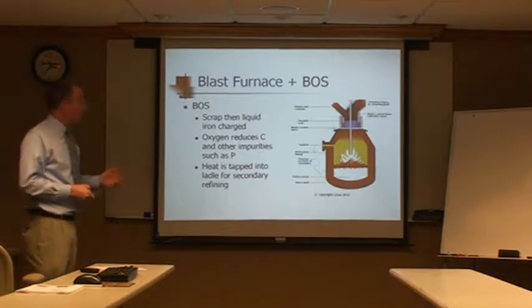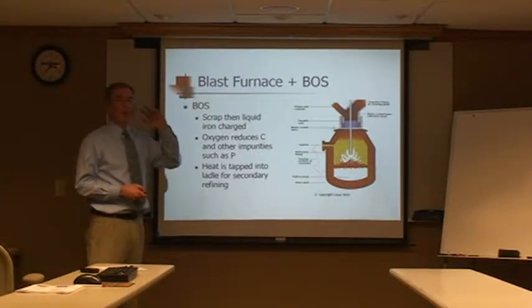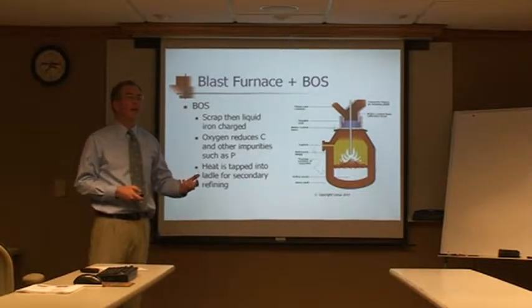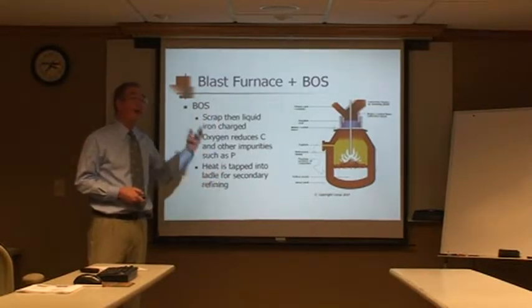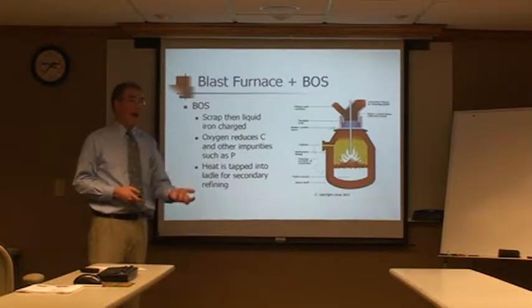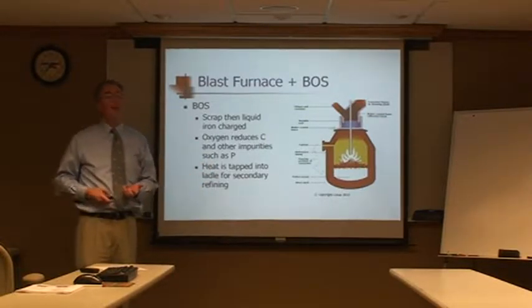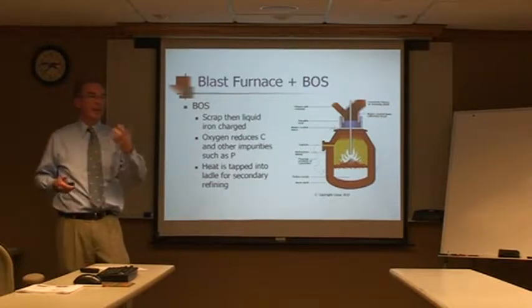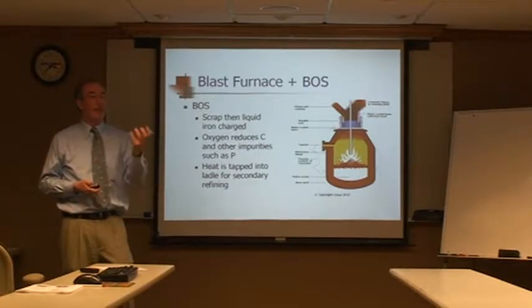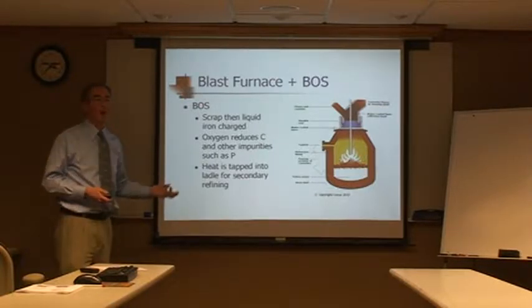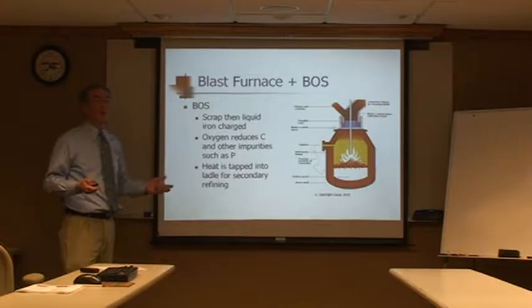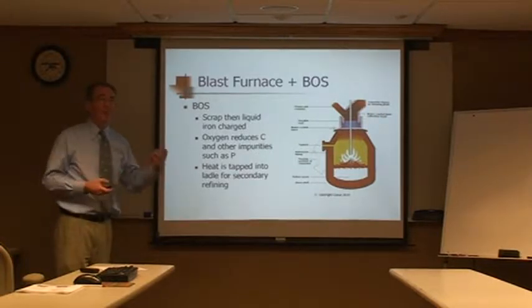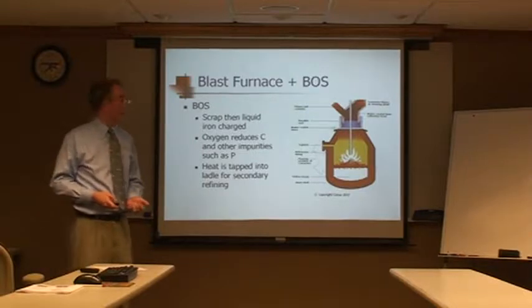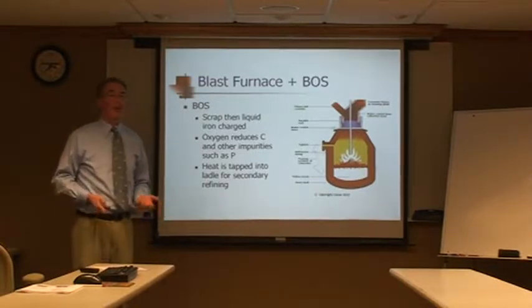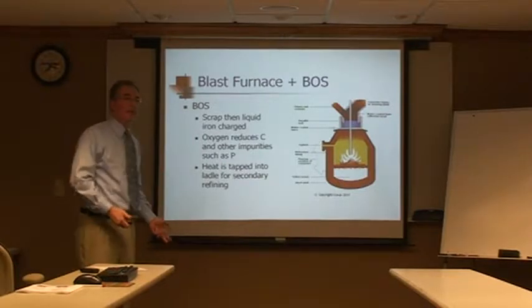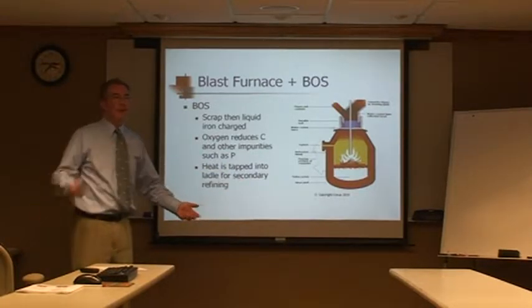Because in the previous step, we were able to get rid of the oxygen by having the carbon react with it, so we're left with the iron. But a byproduct of that is we have iron, but we also have very high carbon. So now we have to get rid of the carbon to be able to begin to make the steel. It's 5–6% carbon probably, 3, 4, 5, somewhere in that range, much higher carbon than we would want for any grade of steel that we would make. So how are we going to get rid of the carbon that's in the liquid iron? Add oxygen. Add oxygen, that's right.